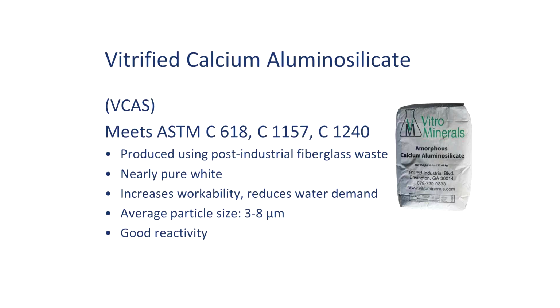The average particle size is 3 to 8 microns, although just like sand, there's all different size ranges. Typically about as fine or finer than cement. It has good reactivity, which is why it's used. So the reason why it's used is it gives you great workability. It's white, so it doesn't affect your colors. You can make pure white concrete with it. It's a green product.